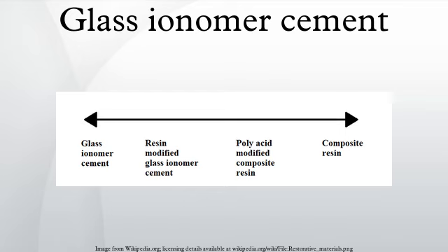In the days when many GICs were radiolucent, the addition of silver conferred radiopacity without which it would be difficult or impossible to diagnose secondary caries. Nowadays, many conventional GICs are radiopaque and are easier to handle than the silver-containing materials. Nevertheless, many workers regard GICs as inadequately strong to support major core buildups. Hence the recommendation that a tooth should have at least 2 structurally intact walls if a GIC core is to be considered. In our view, it is best to regard GIC as an excellent filler but a relatively weak build-up material.